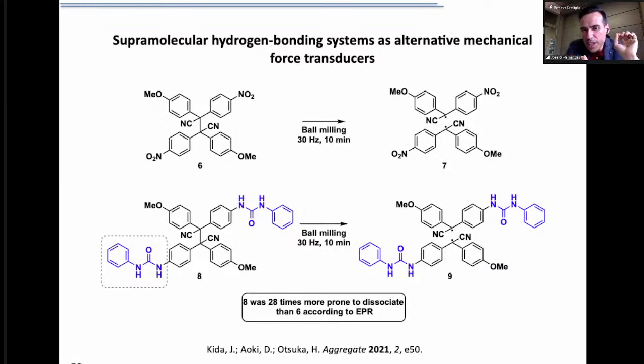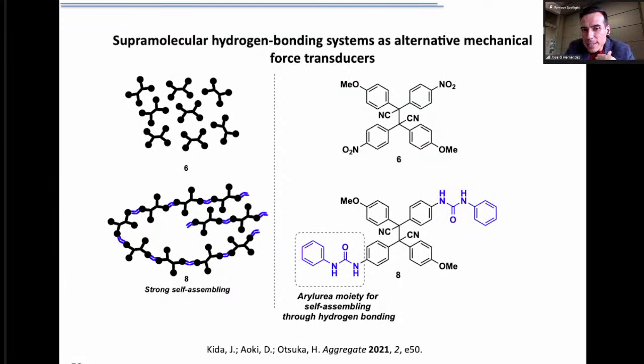However, when the authors compared the reactivity of molecule number 6 and molecule number 8, they observed that the second one was almost 30 times more active towards the generation of the radicals. So the question is, is it because those groups here somehow end up stabilizing the radical that is formed? Or is there something else going on? Well, they demonstrated that what happens is that when you try to grind molecule number 8, it is always trying to self-assemble, generating molecules which are larger in volume and in size. And then the transduction of mechanical force is more effective.